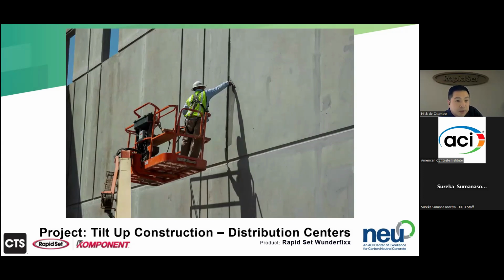This is rapid set Wunderfixx being used to patch bug holes and any imperfections on tilt-up construction at a distribution center. Wunderfixx is a sandless material that can be used to patch up any bug holes or imperfections on a wall. The beauty of this product is that it is sandable, so once you put on your finish, if there are any imperfections or areas that need to be brought down to a surface plane, you just come through with sandpaper and get that down to the finish you're looking for.